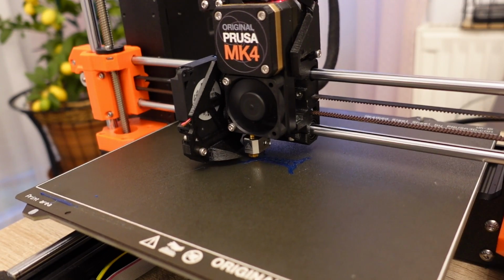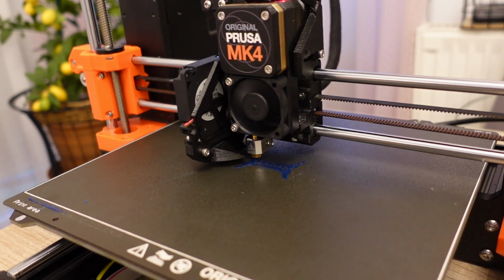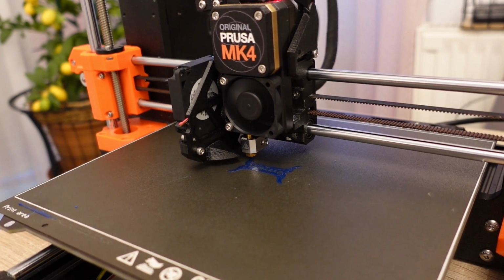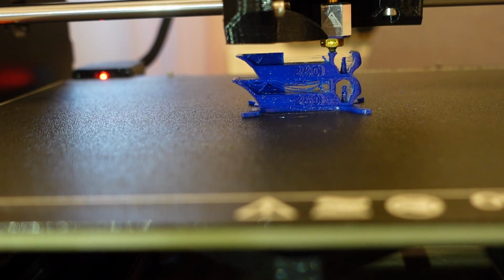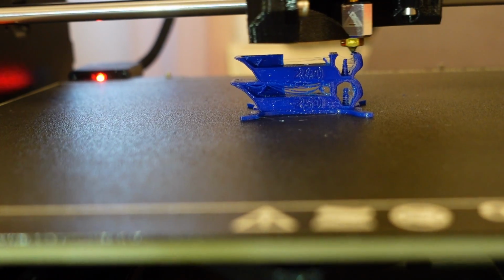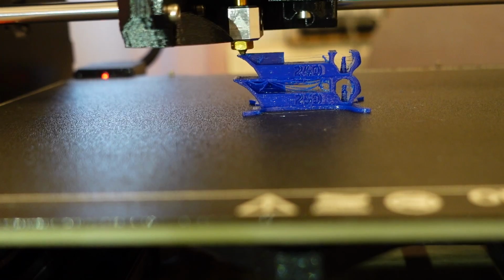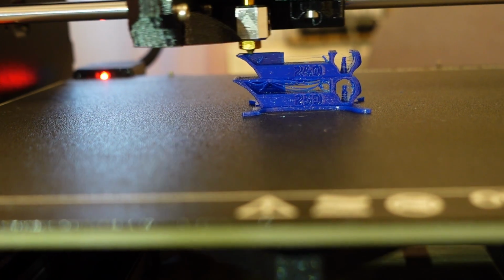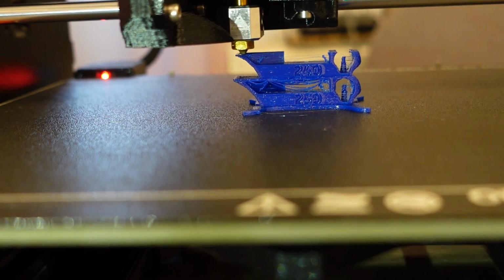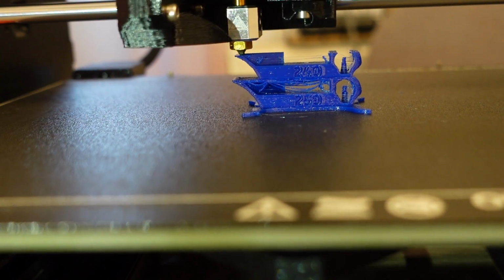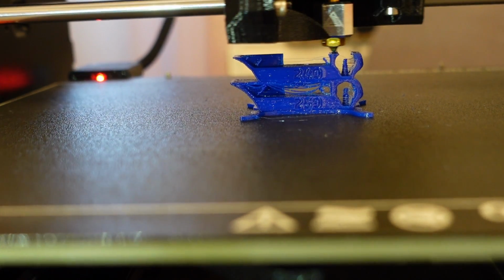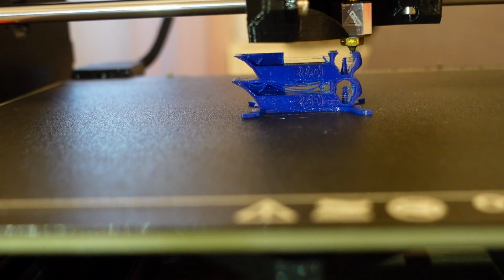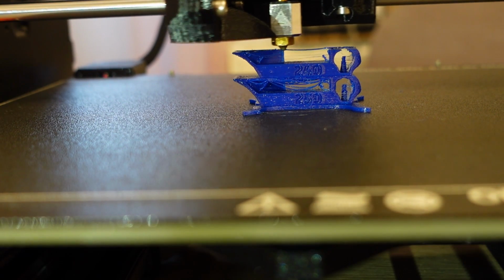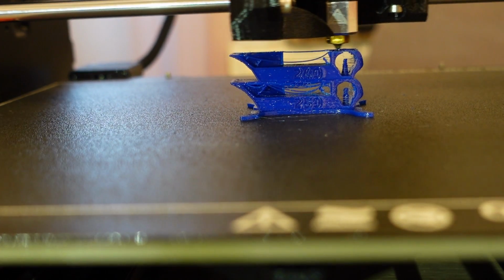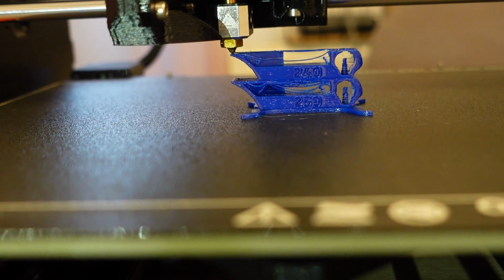The first layer looks good, only it's a little bit hard to see on the camera because of this dark blue color. In theory I should have more stringing problems here compared to the previous filament, but it is cleaner here. The other problem I can see is the bridging currently on that highest temperature element. So definitely those 4 hours of drying help. And finally I could catch the bridging moment. And here you can see the problem, this bridging is too big.